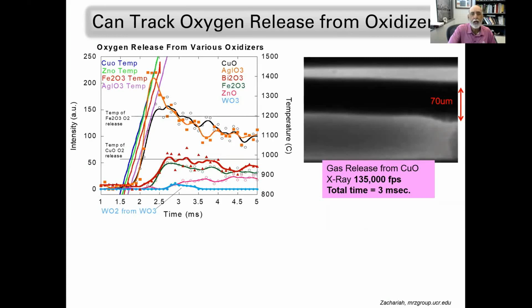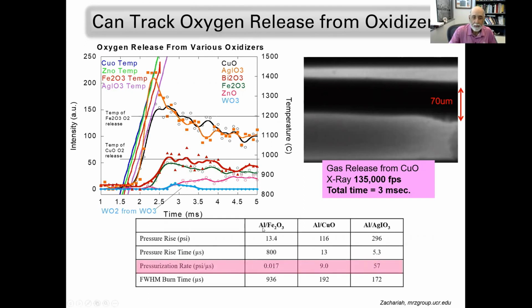And of course, since oxygen is coming out, we can put it in our mass spectrometer. And as a function of time, you'll see peaks for oxygen. And these are different oxygen peaks for different oxidizers. So different oxidizers are going to generate oxygen at different temperatures and at different rates. And that should, in principle, have a big impact on how it reacts with a fuel such as aluminum. And so, in fact, if you look at something like the pressurization rate, which is you put everything in a little closed container and you light it, you can see that the pressurization rate, which is pressure per unit time, can vary depending on the oxidizer. Iron oxide is very weak, silver iodate is very high, and that actually corresponds with the ordering of the oxygen release in our mass spectrometer. So these two things must be connected.